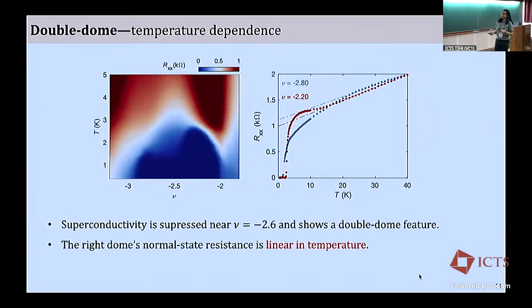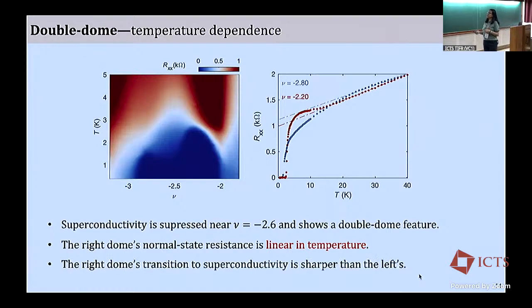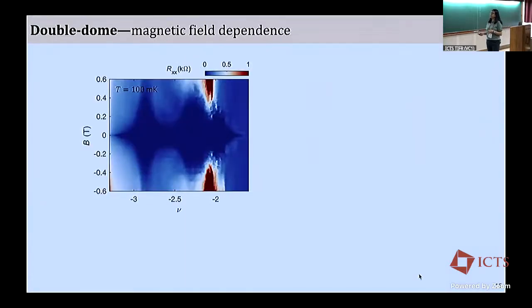And so the right dome, the normal state is linear in temperature, and the left dome is way more like, the transition is less sharp than the previous one. So then we also put in a magnetic field, and in the magnetic field, you can see that basically the same superconducting state is now developing something in between, which can be a charge density wave or something like that. But this is what we see.